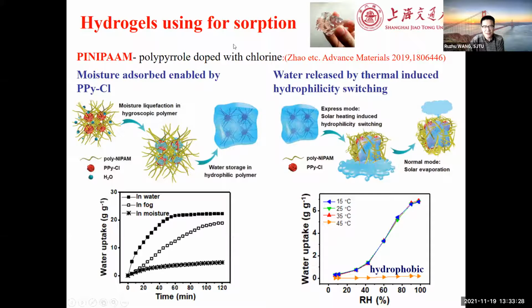Another thing is hydrogels used for the sorption process. If you have some micropores that adsorb moisture, for example with some lithium chloride, then you get adsorption, and the hydrogel will expand, and the water will react with the polymer to form a long chain. But if you just raise the temperature a little bit, to 45 degrees for example, it changes from hydrophilic to hydrophobic, and the liquid could be separated very easily. This creates another application: the hydrogel could be used for atmospheric water adsorption and atmospheric water harvesting.